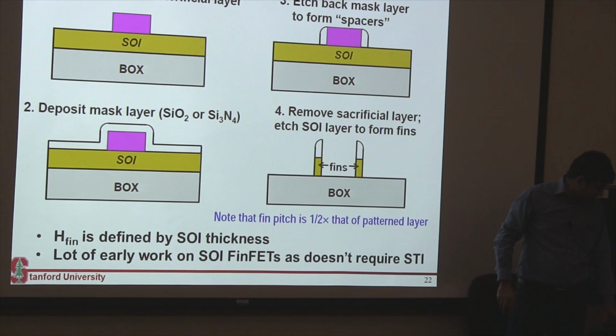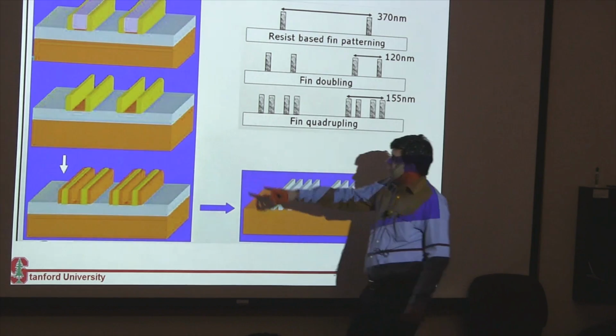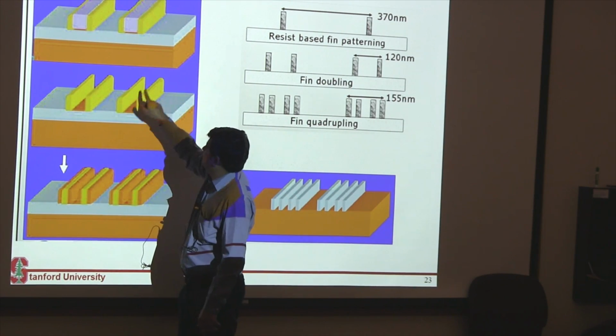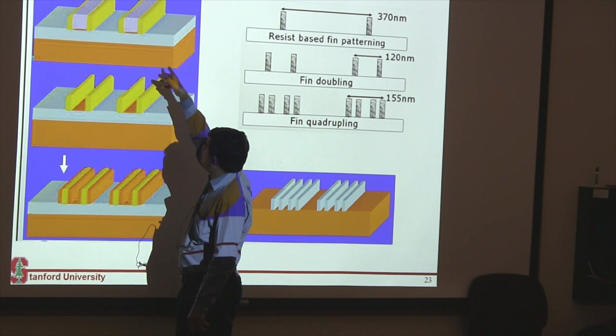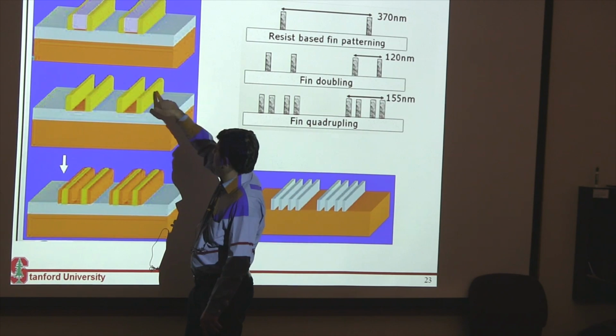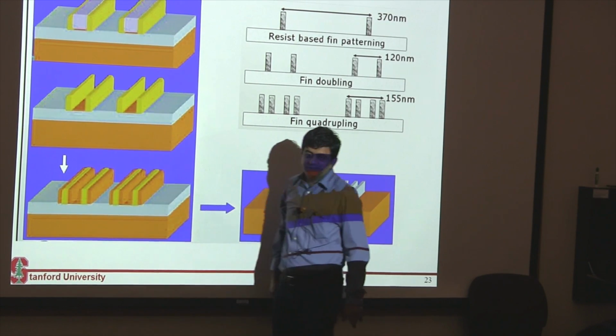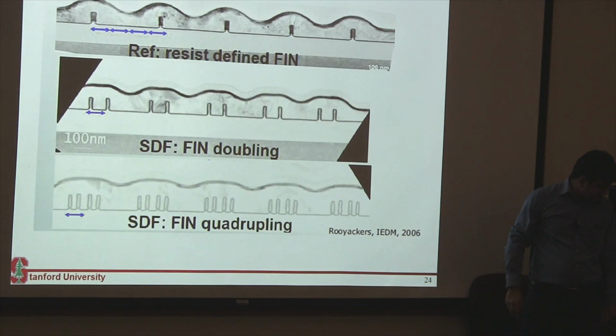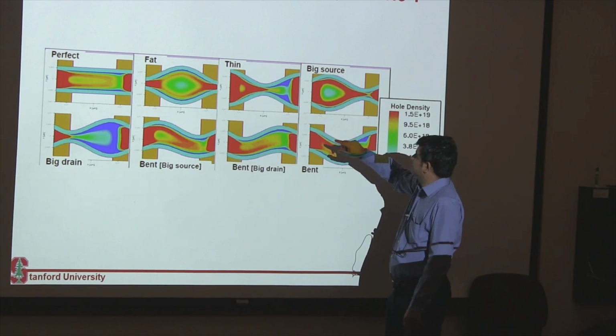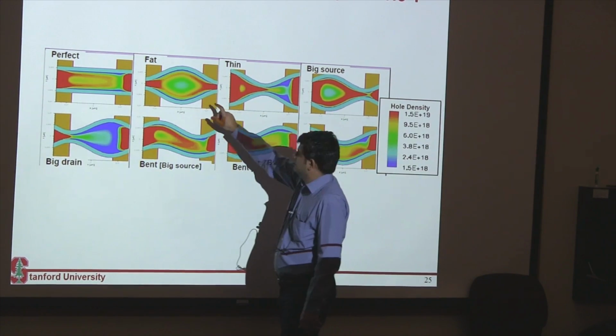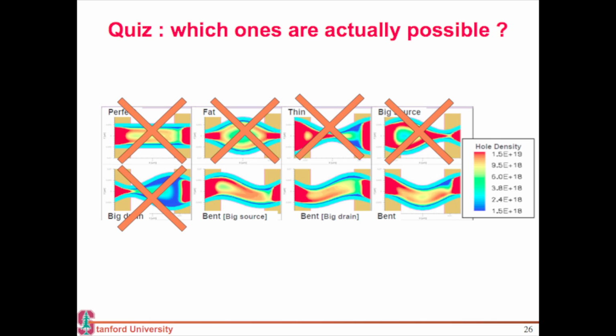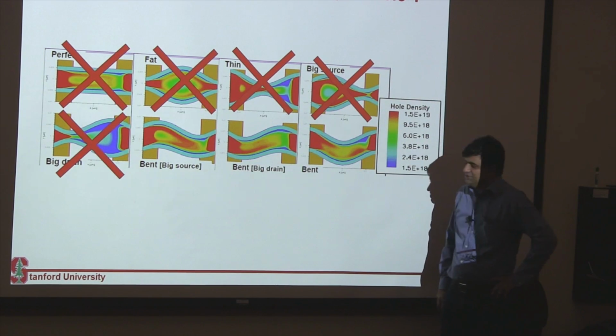If you patterned a mandrel, you patterned essentially this layer, and then you defined a spacer on top of it. So let's go back here. Suppose you had a roughness in this layer, your mandrel, and it was rough. When you deposit the spacer conformally around it, the outer edge of your spacer would have the same roughness. So your roughness between your inside and outside layer are always correlated. So this is not possible, this is not possible, this is not possible. We can rule these out. If you use spacer-based lithography, you cannot get patterns like that. You will always get patterns where the roughness between the inner and outer layer is correlated to each other.